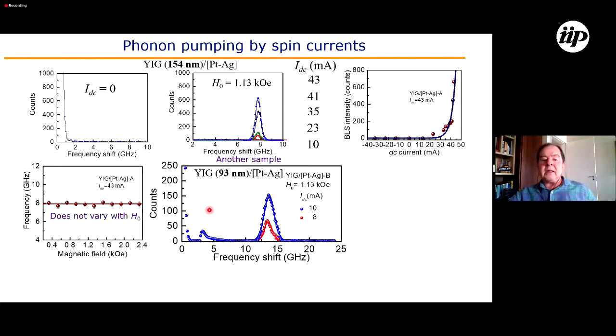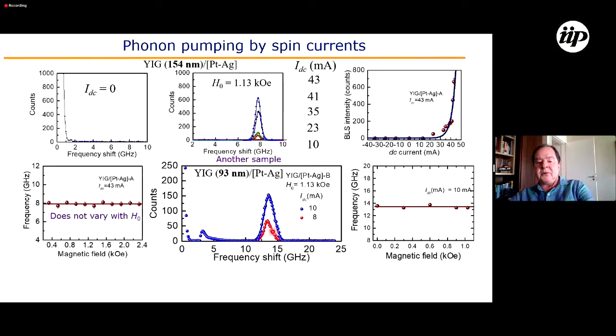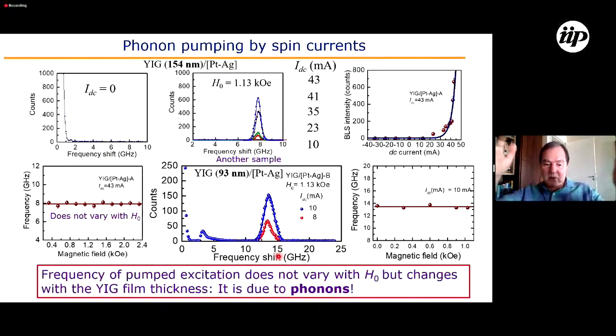We change the thickness of the YIG film. Here we have a film with 154 nanometers. Now we have a film with 93 nanometers, and then the frequency is larger. And the frequency does not vary with magnetic field either. So the conclusion is that a peak in the scattering that does not change with field, but changes with the thickness of the sample is not due to magnons, it's due to phonons.